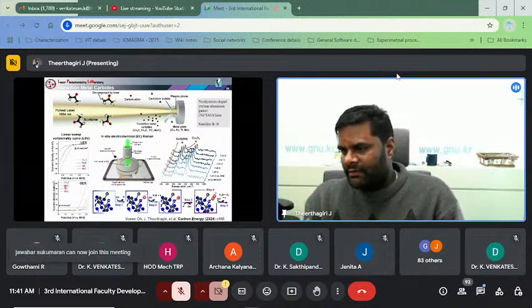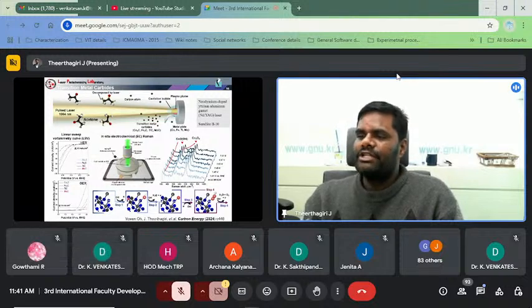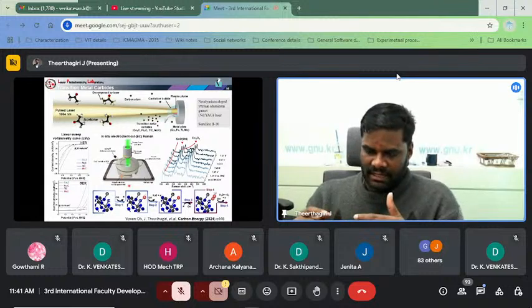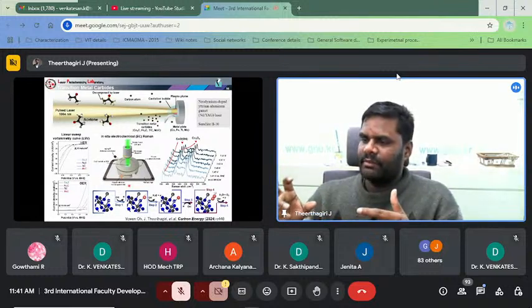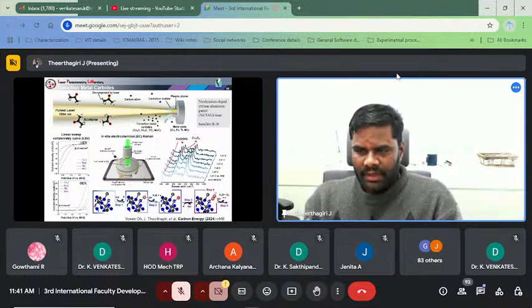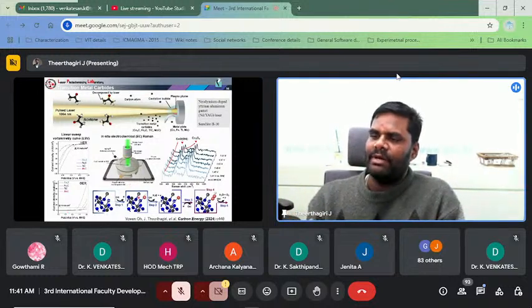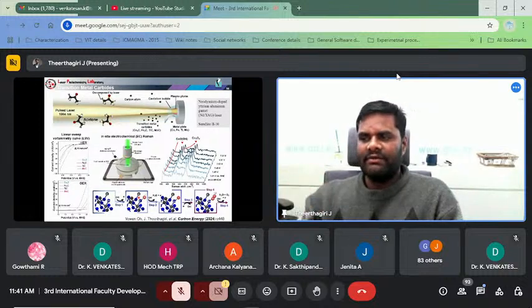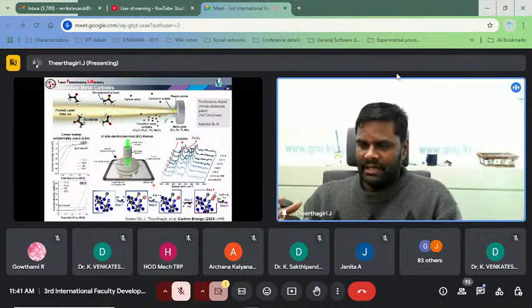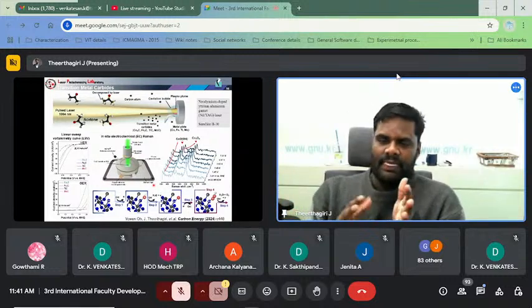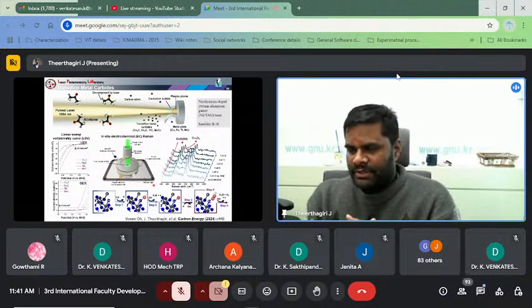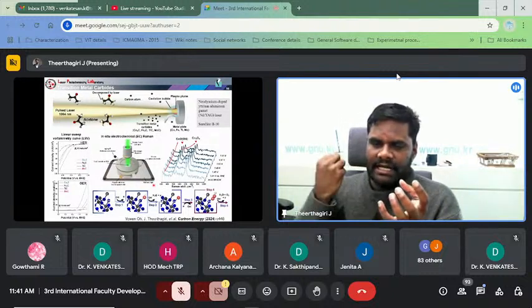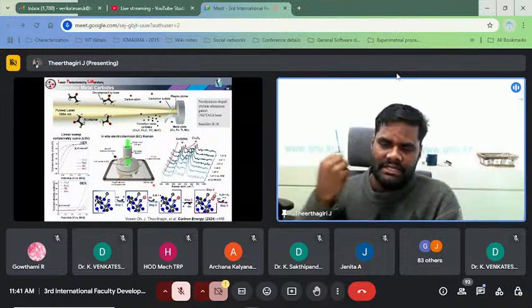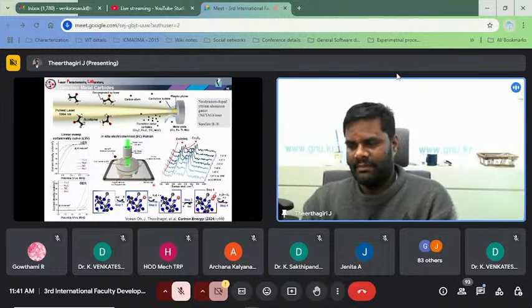I have shown one example using the in situ electrochemical Raman technique. During the electrochemical reaction, we measured the Raman spectrum to see what is happening during the OER reaction. I showed only the OER here, but we studied HER and hydrogen with various techniques also. We study in situ techniques to see how the reaction performs and what happens during the electrochemical reaction. Cobalt is easily attacked; its affinity towards oxygen is much higher compared to other materials.